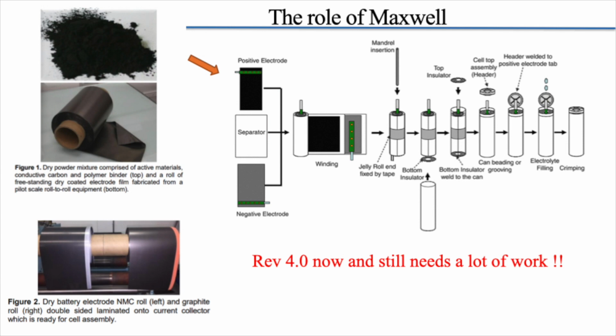And what it does is, they charge it, and during that time, lithium ion goes from the positive electrode, whether it is NMC or NCA, to the graphite or silicon, and in this process, a thin layer of electrolyte interface, called the solid electrolyte interface, forms on the negative electrode, which is graphite or silicon in their case. This process takes a couple of days. Maybe they were able to accelerate it, and they know exactly at what temperature, at what voltage, and what conditions we can do this quickly.